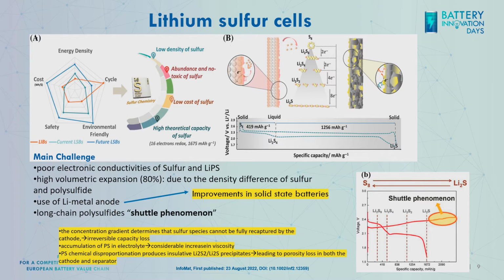It means that we can lose polysulfides during discharging, and this reduces the overall capacity. So we have 2 issues. One is related to the electrolyte. The viscosity of the electrolyte changes a lot during cycling. And also, we can lose capacity because these polysulfides can be self-discharged directly on the anode side.